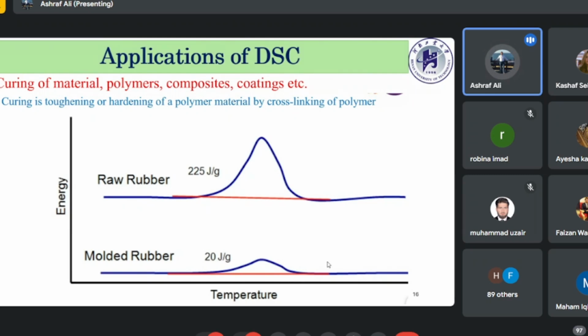So look at these two curves. You can see that the raw rubber has a heat energy of about 225 joule per gram, while the molded rubber shows 20 joule per gram. So the curing in the raw rubber is much more than in the molded rubber, and we can find out the difference between these two rubbers on the basis of their energy.